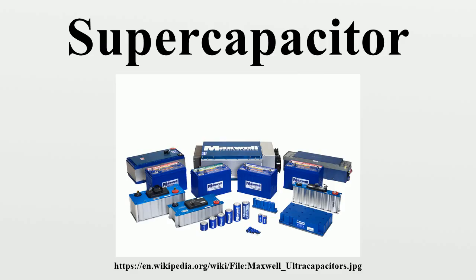Hybrid capacitors, such as the lithium-ion capacitor, use electrodes with differing characteristics, one exhibiting mostly electrostatic capacitance and the other mostly electrochemical capacitance. The electrolyte forms a conductive connection between the two electrodes, which distinguishes them from electrolytic capacitors where the electrolyte is the second electrode. Supercapacitors are polarized by design with asymmetric electrodes, or, for symmetric electrodes, by a potential applied during manufacture.